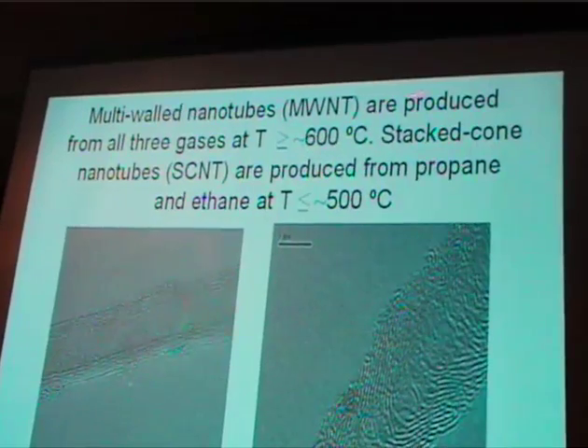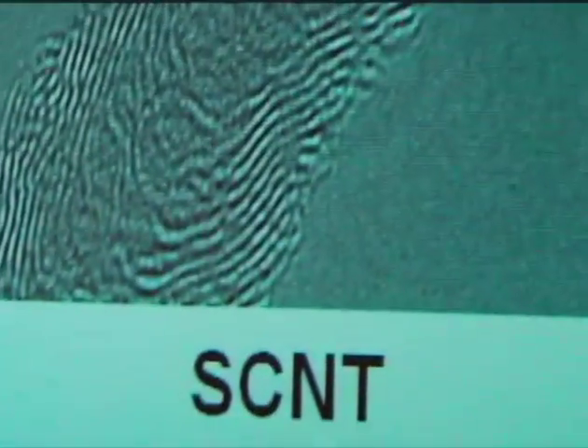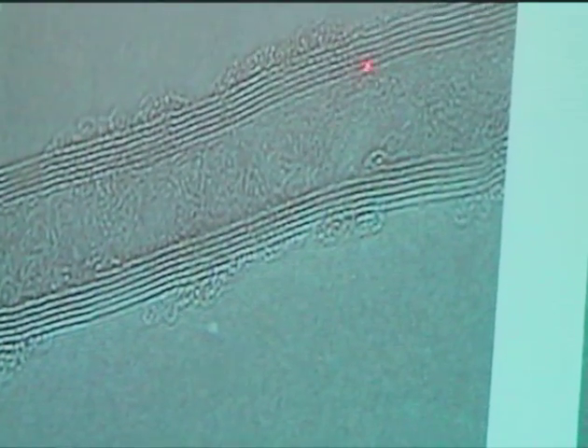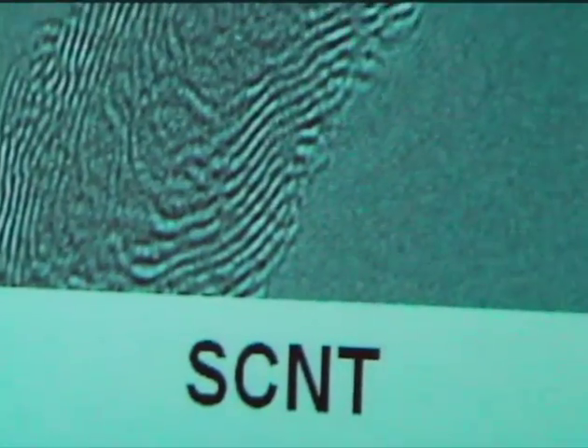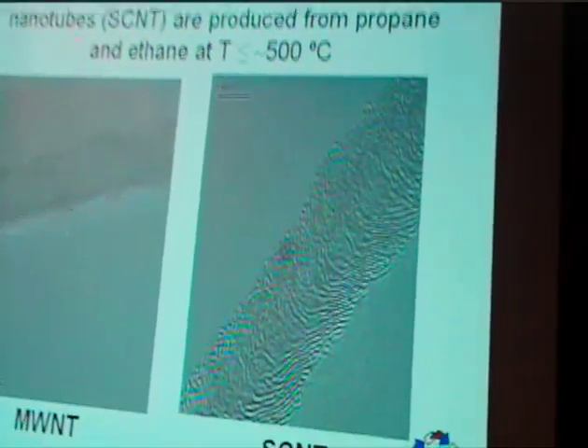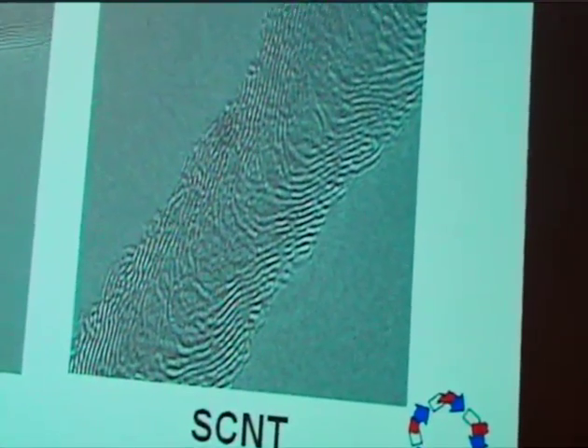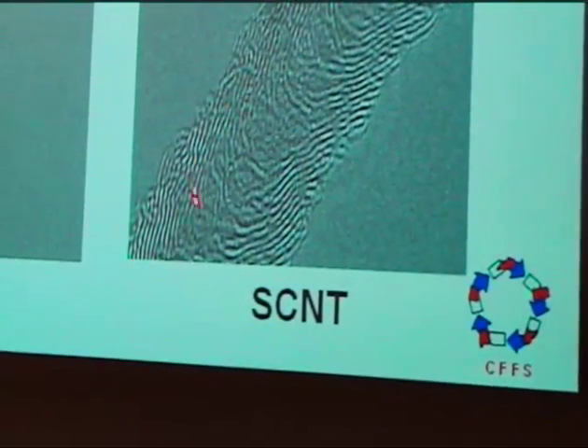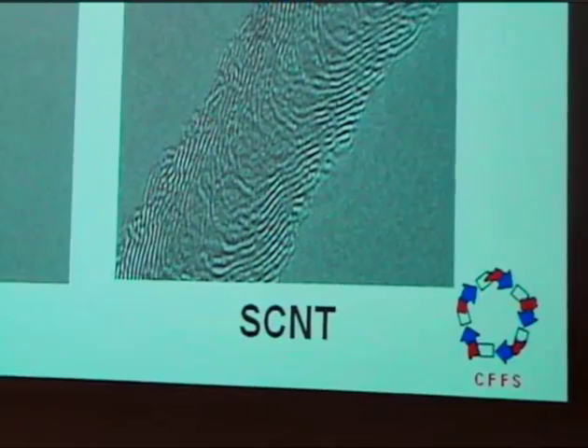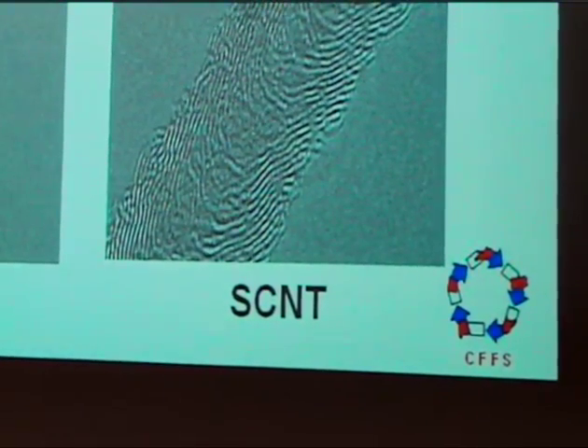If you're in the more active hydrogen production region above 600 C, the nanotubes all turned out to be multi-wall nanotubes, and this shows the parallel walls of one of the multi-wall nanotubes produced. And if you drop down below 500 C, then you find that you're producing stacked cone nanotubes, and you can see the cone-like structure here, those